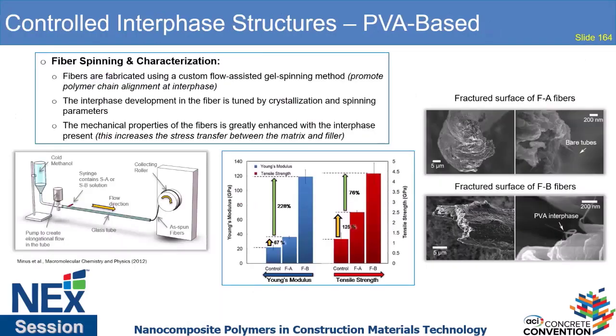So early on, before we understood phase separation or had been using that, the first set of fibers that we were making utilized that data that I just showed you about controlling the interphase using crystallization of the polymer around the nanomaterial. So for a polyvinyl alcohol system, we were able to use a setup in our lab where essentially it's a dry jet wet spinning, but we utilize some flow in order to create some elongation of the fibers as they're being spun. And what we did was we incorporated crystallization of the polymer at the interphase in some fibers, and in other fibers we just dispersed our nanomaterials in there.